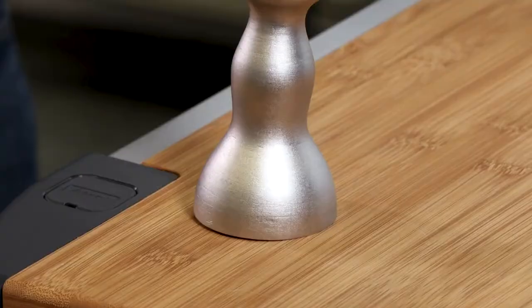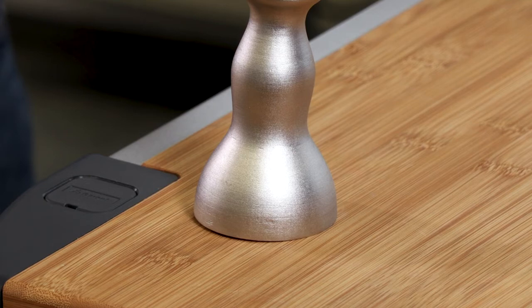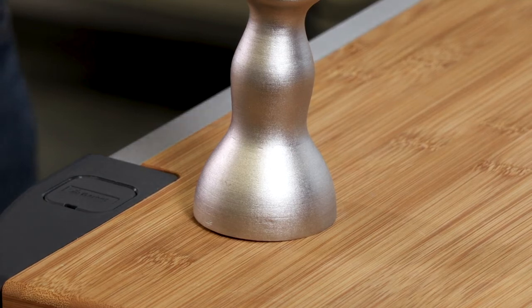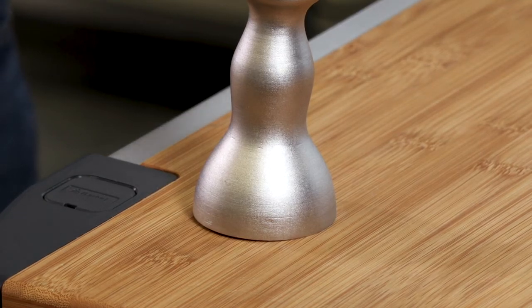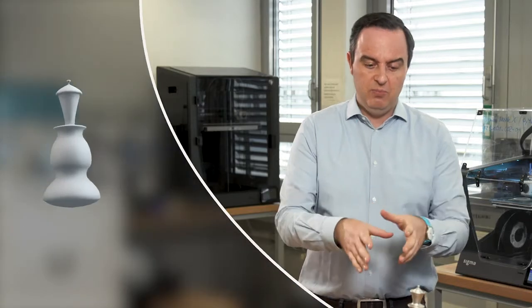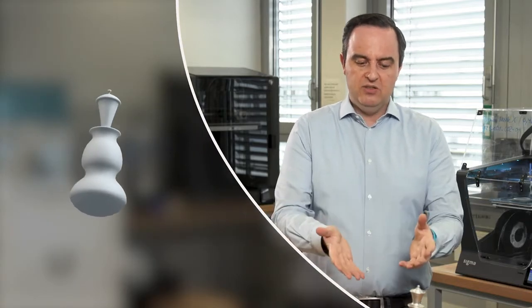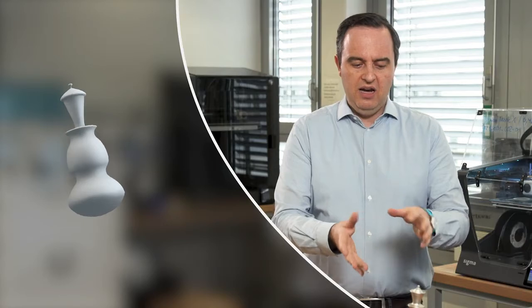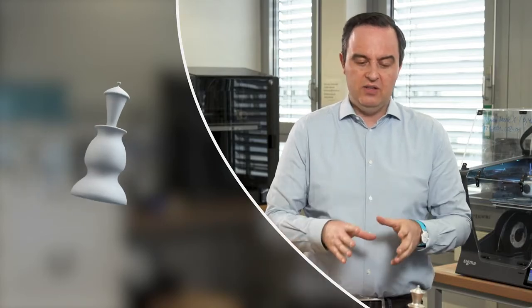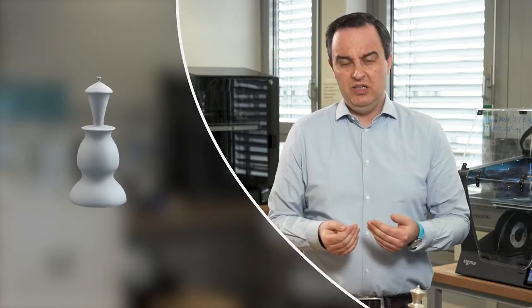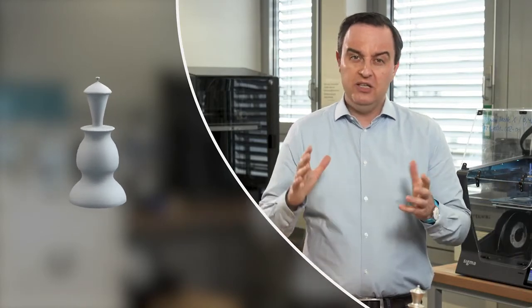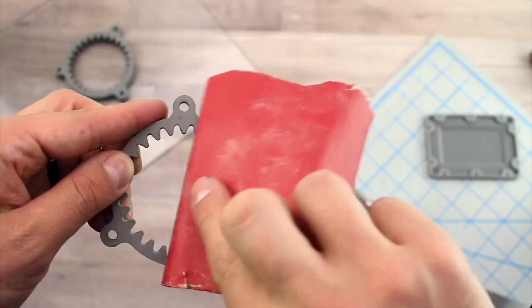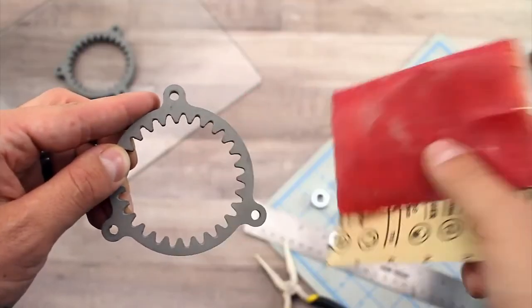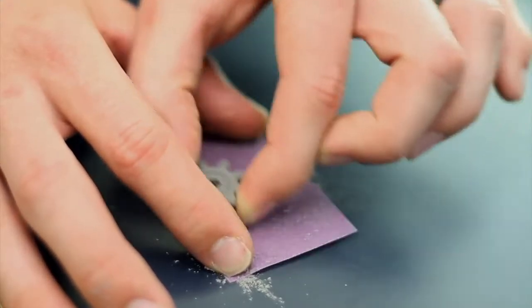And you can see in this, one of our queen figures, we allowed it to warp in the printing process and then sintered it to show us an example of how much lean you can get even with a big part where we have a nice big support and the height to width ratio is okay, but still we're having that effect. So this is easily remedied. You can use sandpaper or milling or cutting, but just sand the bottom of that part until it's perfectly flat to prevent this leaning tower effect.